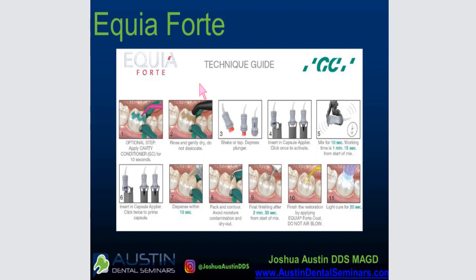So you mix it, load it up into your applicator, your glass ionomer applicator, and then you take it to the tooth and bulk fill it in. You do some minor shaping. Is this going to handle like a G-aenial, a really nice high-end nanohybrid composite? No, it's not. It's going to be more runny than that. It's going to be a little bit harder to carve anatomy into while it's still setting.